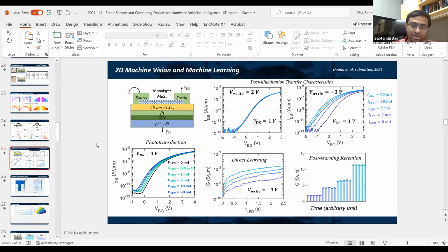There is another paper that I recently reviewed, going to come out in Nature Electronics, where they say that when you are growing these 2D materials, you get a lot of sulfur vacancies. Typically we feel oxygen exposure to this 2D material is bad. But this group from MIT has shown that doing the growth in the presence of a little bit of oxygen can heal those sulfur vacancies. That leads to better photoluminescence, photo response, as well as better contact resistance.